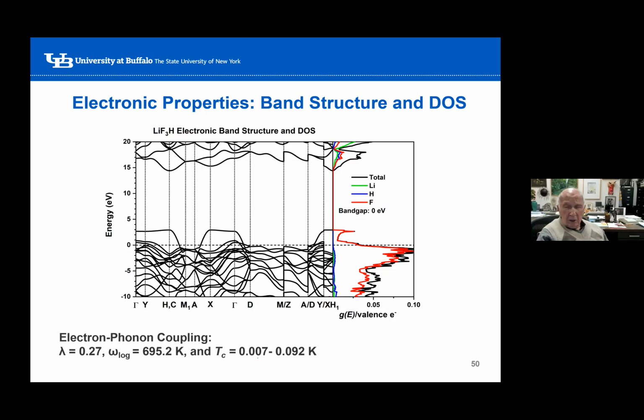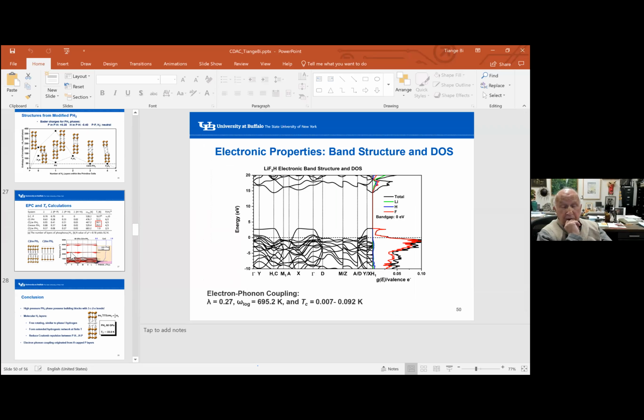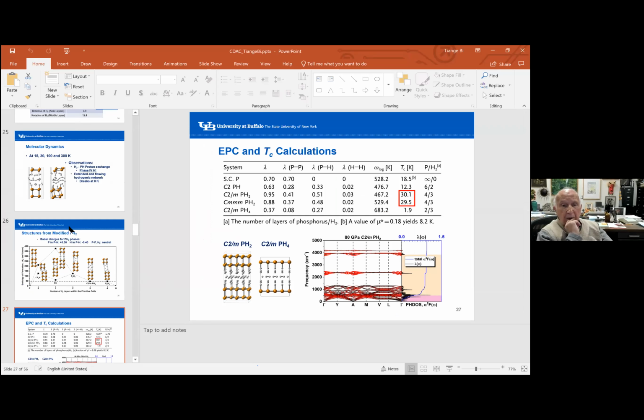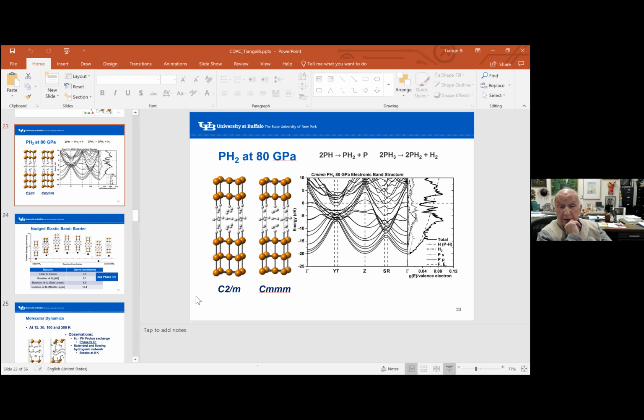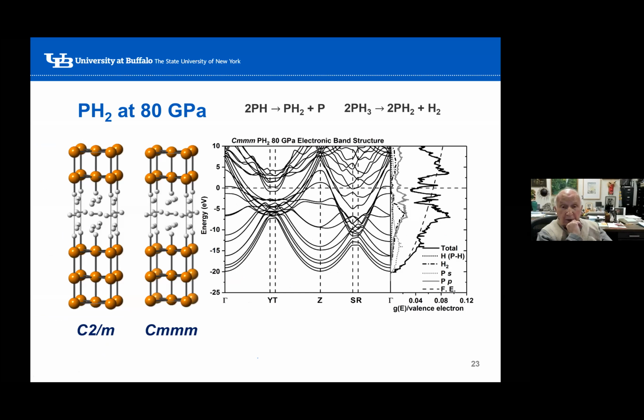I had a question, it's Roald again, back to the phosphorus. Some of those PH₂ structures came from layers of elemental phosphorus and layers of hydrogen. That's a natural starting point, since the elements are thermodynamically more stable than PH₂. So when you optimize the structures, some of the H₂ decomposed and bonded. But the phosphorus retained pretty much the simple cubic structure that elemental phosphorus has at 50 GPa, and presumably it's there at 80 GPa.